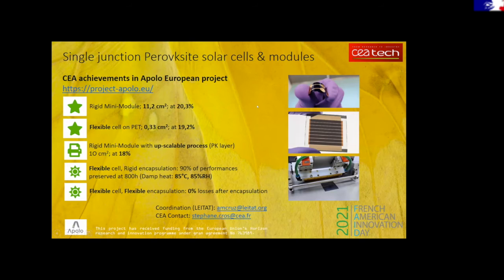In this project, we are developing perovskite solar cells with flexible substrates. Here is an example of cells we are fabricating in the lab. We are also working on modules, because it is possible to make modules using laser scribing, and we are also working on the upscale. For example, these cells are made with a process called spin coating. You have a drop of the solution and you spin your substrate, but it is not an upscalable process. We want to do it with slot die coating, for example, which is a printing technique for the upscale. It is quite a challenge to achieve the same efficiencies with small and big substrates, considering the crystallization kinetics is a key parameter of the efficiency of perovskite materials, and the crystallization mechanisms are not at all the same with spin coating or slot die coating.